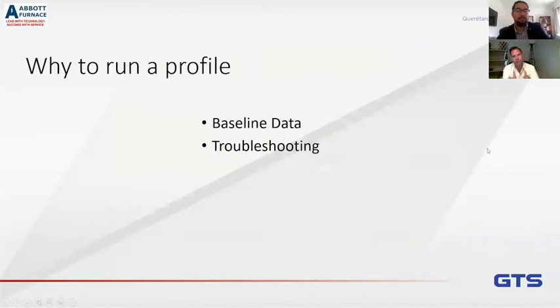Okay. Well, there are 2 reasons that you run a profile. The first is to establish a baseline. And so you should always run a profile when you're making good parts, because you already know you're making good parts, you have a healthy process, so you should establish what that profile looks like that achieves a good part. Right. Then, in the future, if you have a problem, you can run another temperature profile and you can compare them and use those to troubleshoot. And you can say, well, in my baseline, in my good condition, in zone 3, I hit temperature X. Right. But today, I'm not hitting that temperature. Maybe I have some elements out, or maybe something has happened with the insulation. And to your point, so I may not hit the temperature that I need to melt the filler metal and to braze.